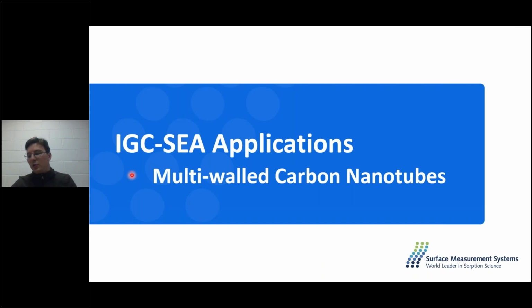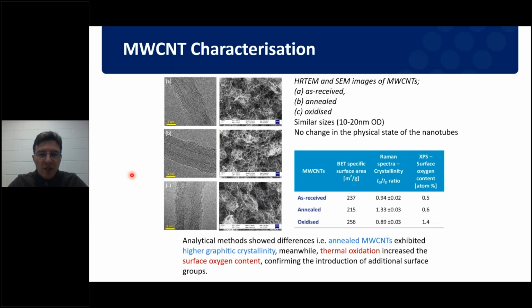Now, it may be a little bit more useful if we talk about these thermodynamic properties with regards to specific materials. So the first case study I'm going to talk about today is going to be multi-walled carbon nanotubes. So here we have 3 different carbon nanotubes that we'd like to analyze the surface energy of. Our first one is as received, so one that's had no further modification done to its structure. We have a surface area which has been calculated. We have done its Raman crystallinity, and then we've also calculated the oxygen content within its surface.